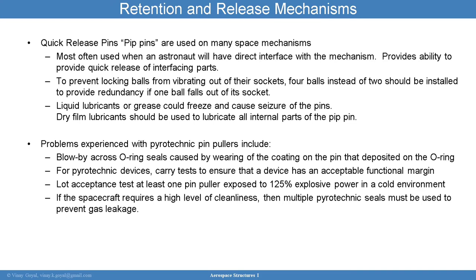You should also look at lubricants, and I keep pointing this out because it is one of the issues that come up quite often. Liquid lubricants can freeze, and that's an issue, and can cause the pins to cease moving. So dry film lubricant should be used to lubricate all internal parts of a pip pin, which is a quick release pin. Problems experienced with pyrotechnic pin pullers include blow-by across O-ring seals, caused by wearing of the coating on the pin that's deposited on the O-ring.